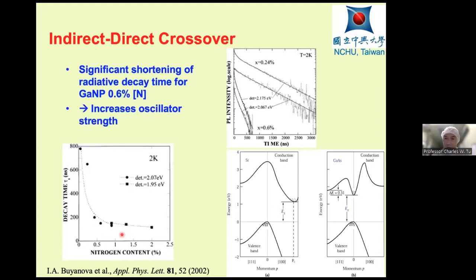Now, short lifetime corresponds to direct bandgap because light emission is efficient. But for indirect bandgap, the electron is here, the hole is here. In order for the electron and hole to recombine to produce a photon, the electron has to scatter with a phonon, a lattice vibration, to lose its momentum to here, and then come down and recombine. And so this is a demarcation of direct bandgap and indirect bandgap theory.